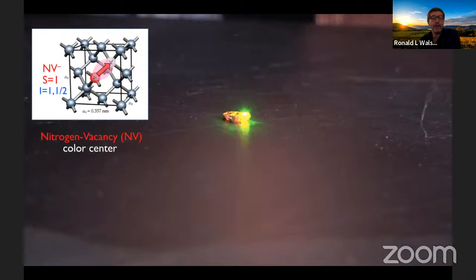In particular, the NV center is energetically favored. That is, if there are nitrogen atoms, remember, nitrogen is next to the carbon atom on the periodic table, and so nitrogen is a common impurity in diamond. If there's a nitrogen atom inside of a diamond replacing a carbon atom and a missing carbon atom or a vacancy, and you heat the diamond up to about 1,000 degrees Celsius, the vacancies will mobilize, and it's energetically favored when they come next to a nitrogen to stabilize into an NV center. You can then cool the diamond back down, and you can have one or many of these NV centers, depending upon how you grow or fabricate the diamond.